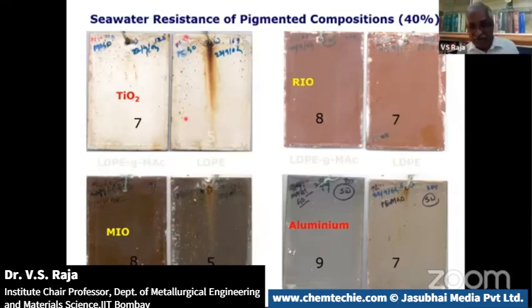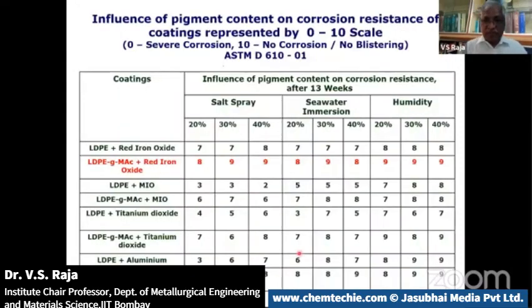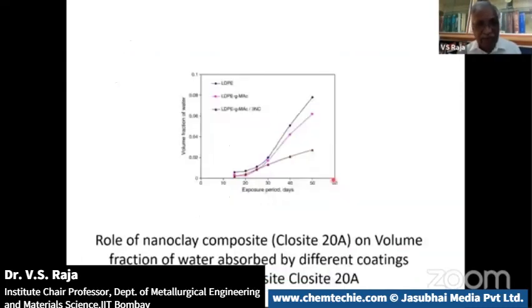We have various kinds of pigments: titanium dioxide, MIO, you can use aluminum. Various types of pigments are being added to determine the performance of these coatings. Don't worry about this table here. This only tells you that we have done detailed studies in terms of salt spray, seawater immersion, and humidity, because the performance of the coating in salt spray, salt fog is different from the immersion conditions, right? So we look at the ways the performance is evaluated here. This is in terms of scale. These are all published, and I can share the data with you. You can go through them very leisurely.